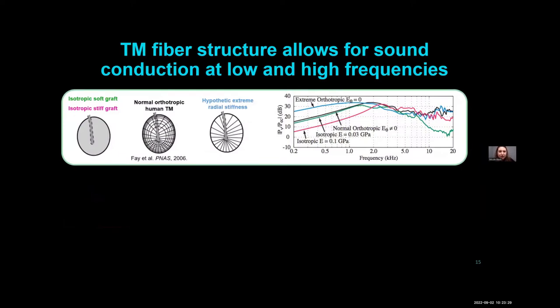And so why is this architecture important for sound conduction? Really your body has engineered this to be able to have your eardrum behave more like a soft material at lower frequencies and more like a stiff material at high frequencies. So as you can see, this is a computational modeling experiment by Sunil Puria's group that's now at Mass Eye and Ear. They were at Stanford, where they modeled the eardrum first as a normal orthotropic tissue. So with its normal properties you see in black, and looked at essentially what is the amount of pressure that ends up being transferred from your ear canal to the vestibule of your cochlea. So that PV over PEC is the pressure in your vestibule over the pressure in your ear canal that's normalized.